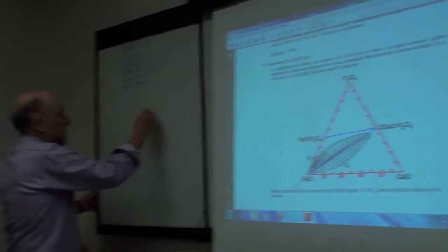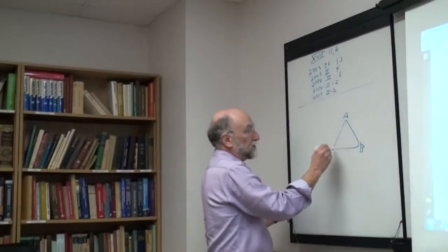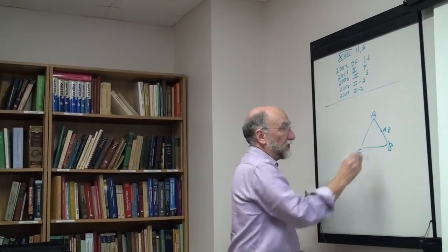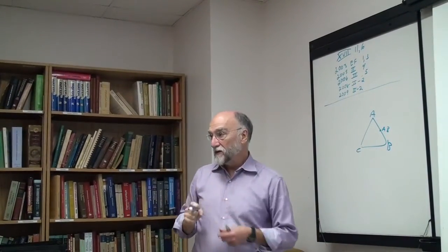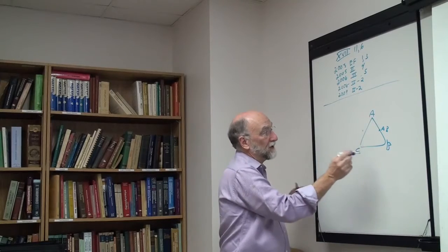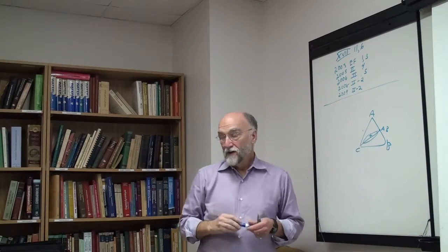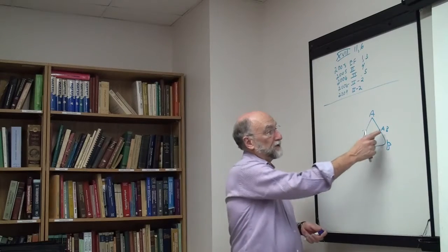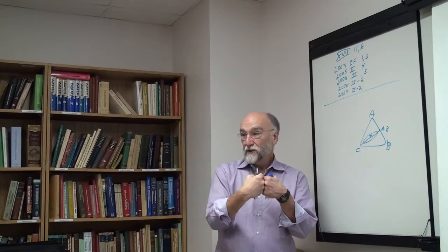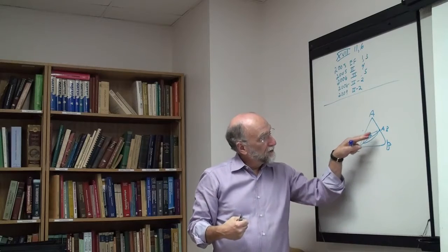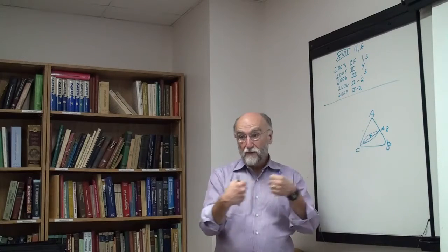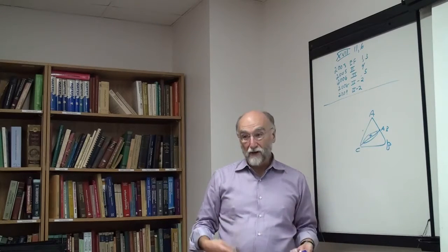Well, it's like the systems that we talked about earlier. If you have A, B, C, here you have strong short-range ordering, like to form A, B nearest neighbors, and here you don't. Then you tend to get positive deviations along this join. The positive deviations because the A's and the B's like to stay next to each other. And if you add C, you're forcing the A's and B's to come apart, and that's giving a positive contribution